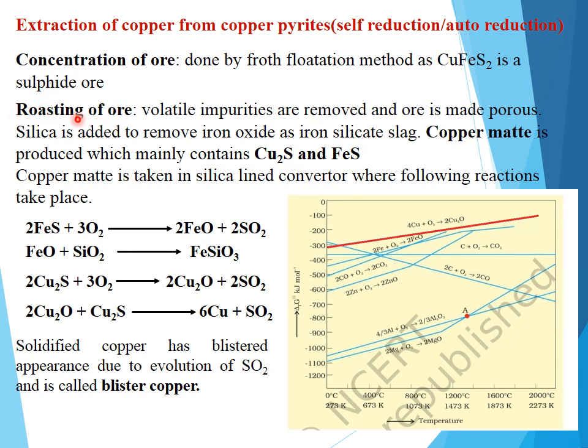During roasting in the reverberatory furnace, roasting is carried out in the presence of an excess supply of air, and at that time silica is also added. The purpose of adding silica is that this ore contains sulfides of iron also, and we need to remove this iron sulfide or iron oxides which are acting as impurities. To remove the oxides of iron, that is ferrous oxide, which is basic in nature, it has to be treated with acidic flux.